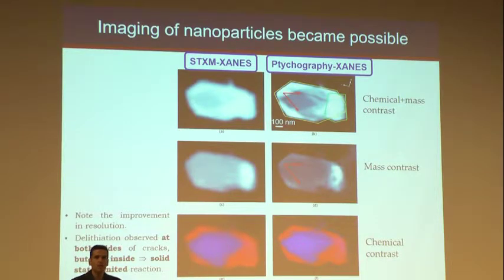And so what we concluded from this was that we have a delithiation front that is going down that flat facet surface of the particle, building up strain up to the point where the particle just fractures, opens up, and it exposes a domain underneath. And that one was not reacted yet. And that's how it continues to proceed. So this gave us clues into the fact that you're limited by the solid state diffusion in your material in these reactions.